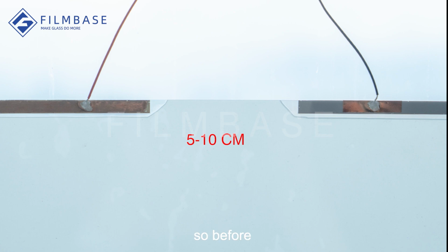The welding. Before this process, prepare 2 black and 2 red cables per window, about 10 centimeters long each. Take off the plastic ends, about 3 millimeters, so that the wires are visible. Remember that all welding dots should be applied on the non-sticky side. Basically 2 dots on the long copper strip and 2 dots on the rectangle copper strip, all on the same side of the smart film.